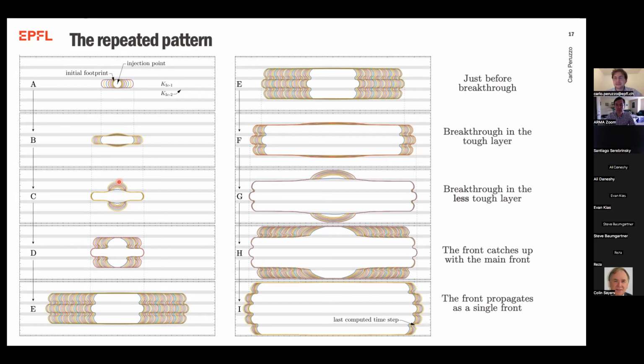Also, I guess industrial. Going back to Ali Danish's point, though, if I have a horizontal well, the stress perturbation around the horizontal well could weaken some of the horizontal interfaces above it, and so as the fracture propagates up, the shear stiffness of the interface could well be lowered. So I think it would be very good to include the possibility of T-shaping, the propagation of the fracture along the interface. Yes, that would be very nice, to have a more accurate model.